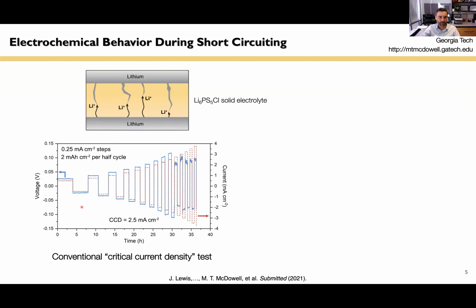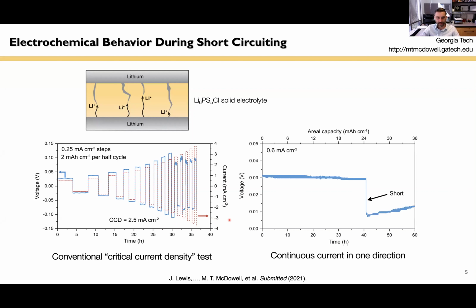The way you do this is you take a cell like this, and then you apply currents in alternating directions, and the currents keep increasing until eventually your voltage falls, and that's when a short circuit forms. This is a degradation pathway, and the formation of these short circuits is a limiting factor in many solid state chemistries. This is what people have seen in the literature, just for reference for those working in this area. We measure an average critical current density of 2.5 milliamps per centimeter squared. This is not new, but I'm showing you an electrochemical measurement of this degradation behavior. What's interesting is that we've carried out a study recently, which is submitted for publication. This sort of short circuiting is usually tested with these CCD tests. But what we've also found, which is known in the literature but not really well quantified, is that if you just apply a current in one direction, basically moving lithium from one side to the other without alternating back and forth, even at very low current densities, you eventually still get a short circuit.